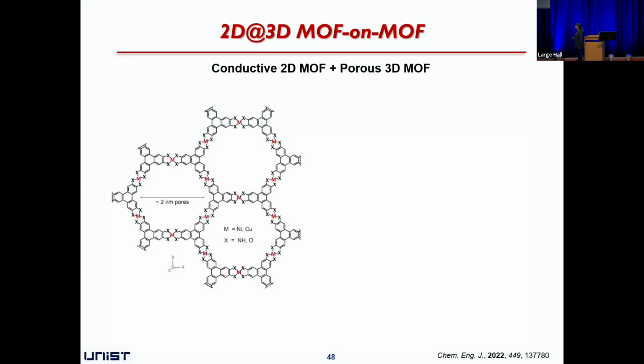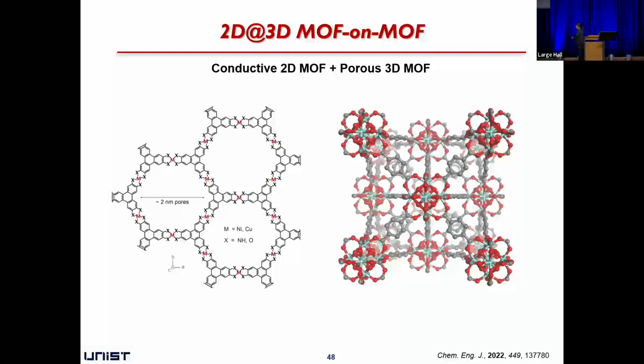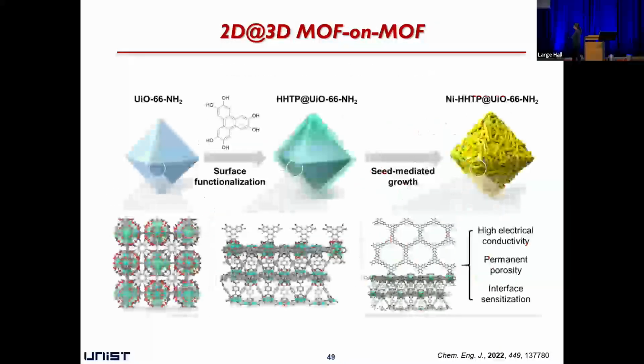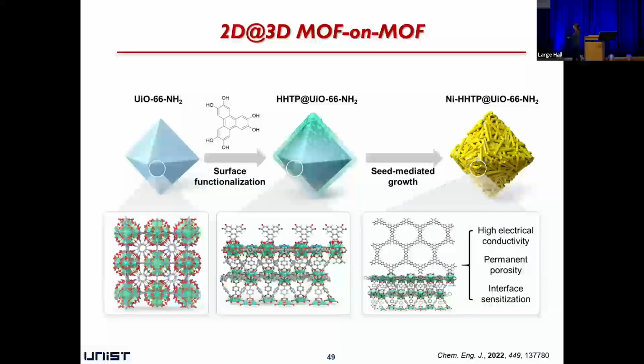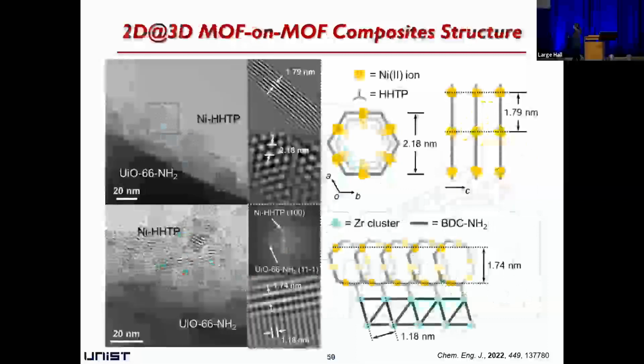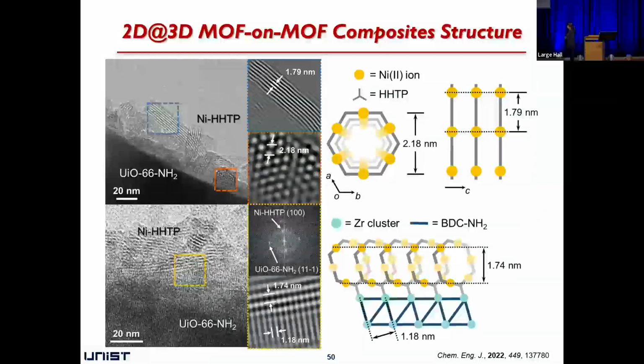The last example is 2D and 3D MOF-on-MOF. Okay, there are already many conductive 2D MOFs reported, and we can have porous 3D MOF. By combining these two different types of MOF, we can think about many interesting applications such as a sensor. So we tried to synthesize this 2D and 3D MOF-on-MOF structure, and we finally obtained this structure. If you see the TEM image, it looks like just a physical mixture, but it is not. If you see the interface between UIO66 and nickel HHTP, you can see the very well connected interface.